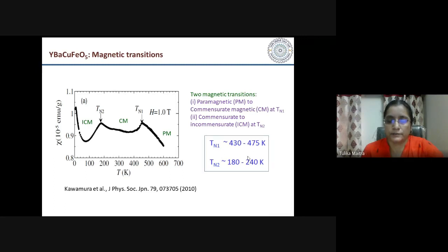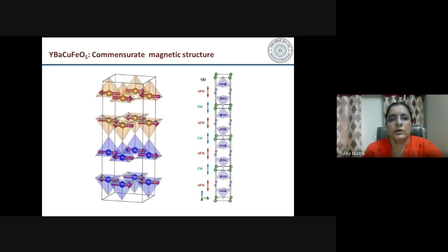There is a whole range being predicted by different experiments because this compound depends very much on how the sample is prepared. So there is a range of temperatures where the first transition is predicted to be. Okay, so there are basically two magnetic transitions here. Now the commensurate magnetic structure looks like this. In the AB plane we have antiferromagnetic order, but these spins are lying in the AB plane. When we move along C direction, then we have antiferromagnetic, then ferromagnetic, then antiferromagnetic, ferromagnetic, like this. So this is the commensurate magnetic structure that is observed in neutron diffraction experiment.